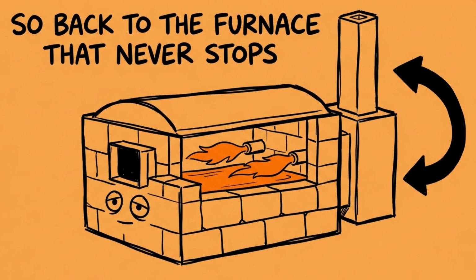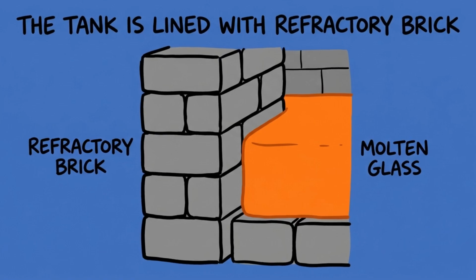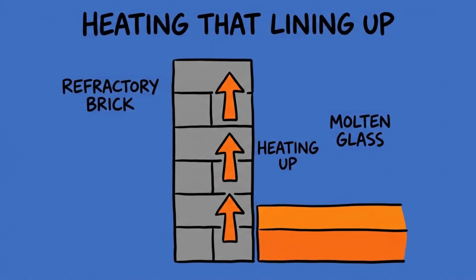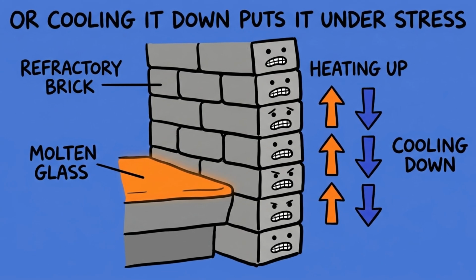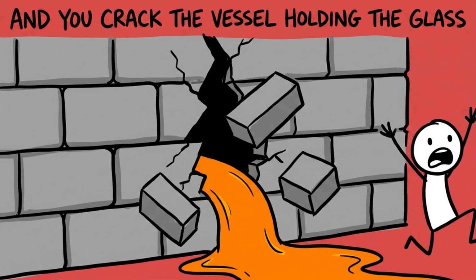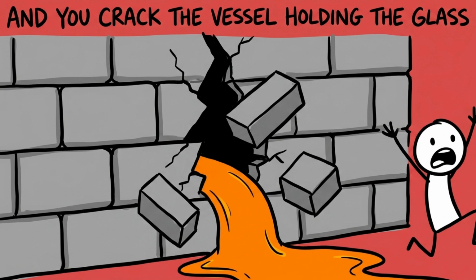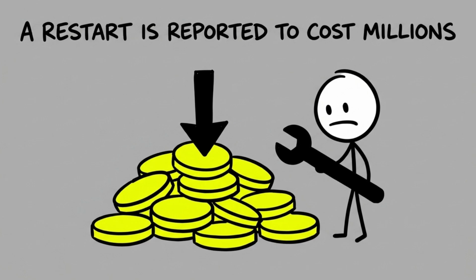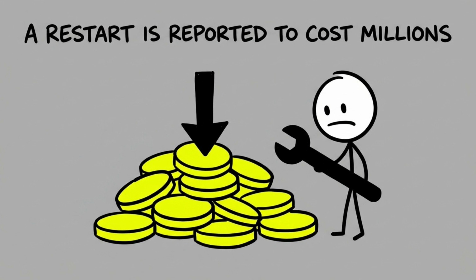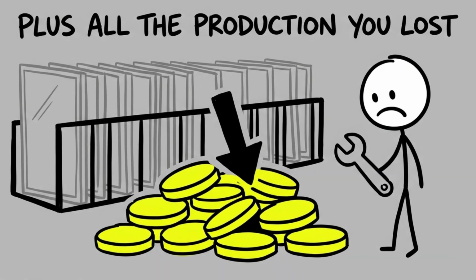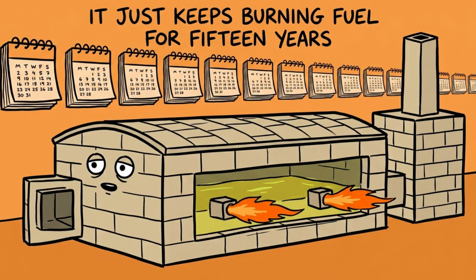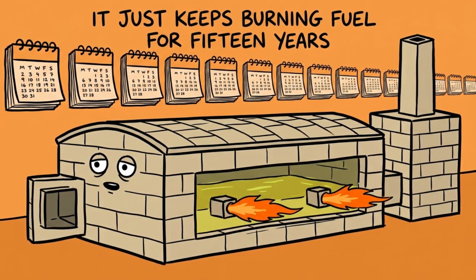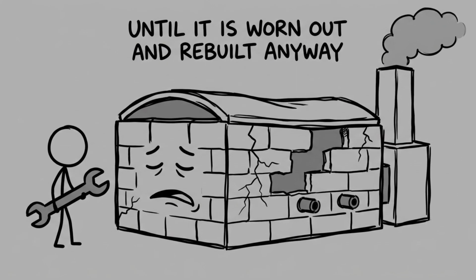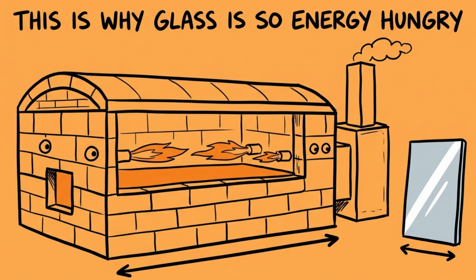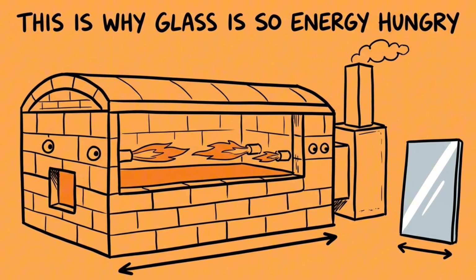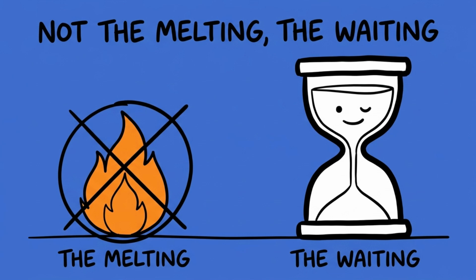So now go back to the furnace that never switches off. The tank is lined with refractory brick, and heating that lining up or cooling it down puts it under enormous thermal stress. Do it carelessly, and you crack the vessel holding 1500 degrees of liquid glass. A shutdown and restart is reported to cost millions in repairs and lost production. So the plant does the arithmetic and simply keeps burning fuel for 10 to 15 years, until the furnace is worn out and has to be rebuilt anyway. That is the honest reason glass is one of the most energy-hungry materials you own. Not the melting, the waiting.